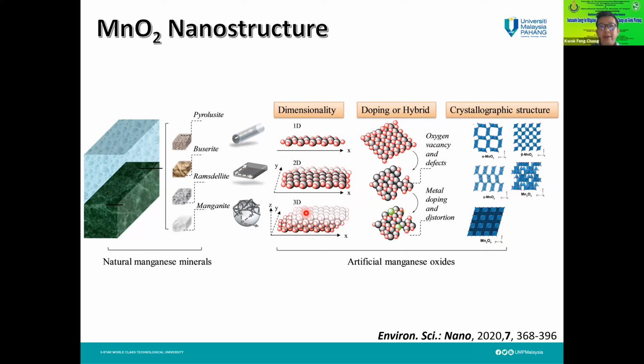We can dope it, and we can do the hybrid as well, so that we can increase the defect or the oxygen vacancy, and cause a distortion of this structure. And the crystallography for this manganese oxide also can be divided into several types. So this is our main focus. We want to see whether manganese oxide can be used to accommodate this aluminum ion.